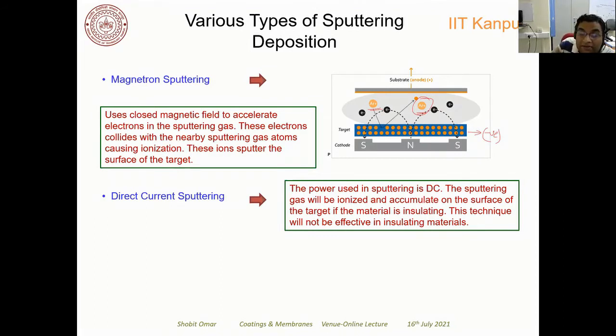Because now this target material is not conducting any electrons. It is an insulating dielectric material, and because of the polarization, these argon ions start accumulating on the surface of the target. So that's one of the drawbacks of using the DC sputtering technique, because you cannot make a thin film of an insulating dielectric material from the DC sputtering technique.